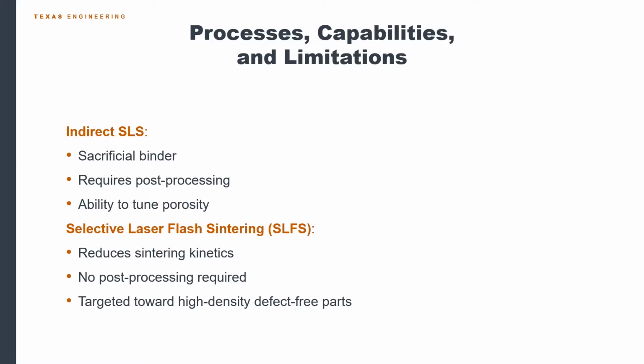The second method to overcome the difficulties with ceramics is by reducing the kinetics of sintering. We do that with a process called selective laser flash sintering, which is very similar to SLS, except that we add an electric field across the powder bed. This method doesn't require any binder or post-processing, and it is targeted towards high-density, defect-free parts.